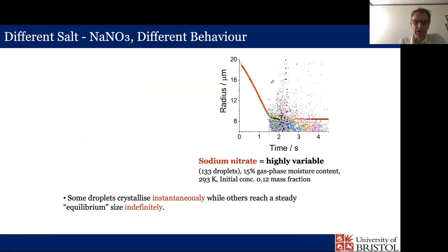But if we have a look at a different salt, again a very simple salt, sodium nitrate, again we got a drying curve, but this time we see some of the particles we seem to be able to track for a long time through their drying. And so these particles, they're not crystallizing, they're remaining amorphous with time, even though they're dried down to essentially their equilibrium